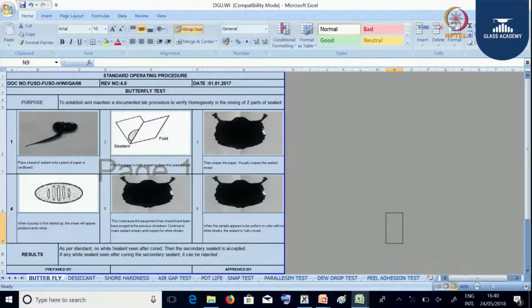When we open, the shape of the sealant shall come like a butterfly, that is why it is called a butterfly test. If once you open the paper you are able to see any white patches in the sealant, then there is a mixing issue. If there is no mixing issue, the sealant will come out black. So through this butterfly test, we are ensuring that homogeneity of the mixing of the two-part sealant is maintained.